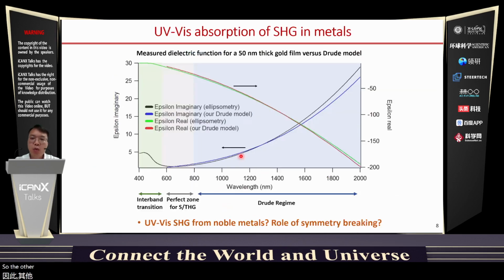The other problem with the previous study is that their second harmonic generation occurs in the visible range where, for example, if you look at this dielectric function, here the left axis is the imaginary part of gold. You find that in their second harmonic generation region, the imaginary part is very small, which means that the intrinsic absorption is very small. So the problem is how we can enhance the second harmonic generation in the UV range, or even the blue range, where the intrinsic loss of metal is actually significant. And how about the role of symmetry breaking in our structures? For this purpose, we have analyzed our plasmonic nanocavities.